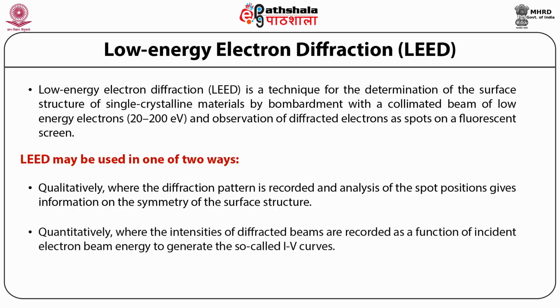Quantitatively, the intensities of diffracted beams are recorded as a function of incident electron beam energy to generate the so-called I-V curve. By comparison with theoretical curves, these may provide accurate information on atomic positions on the surface at hand.